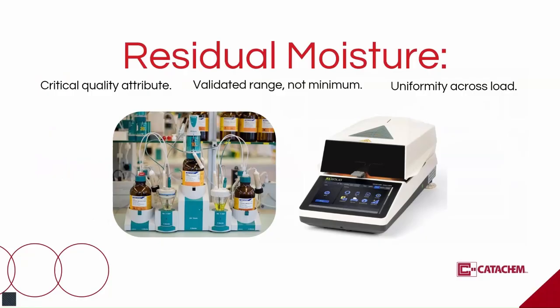Residual moisture is one of the strongest predictors of long-term stability. Too high, and you accelerate hydrolysis, oxidation, and other degradation pathways. Too low, and some proteins can become overly brittle or lose activity depending on the system. The point is not lowest moisture possible. The point is validated moisture range that correlates with retained function and shelf life.